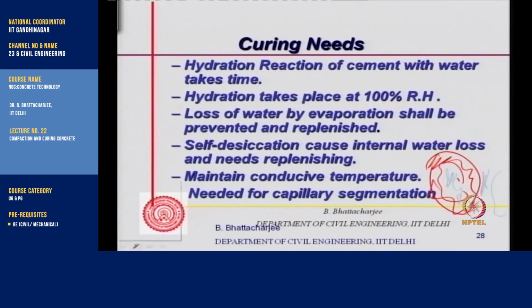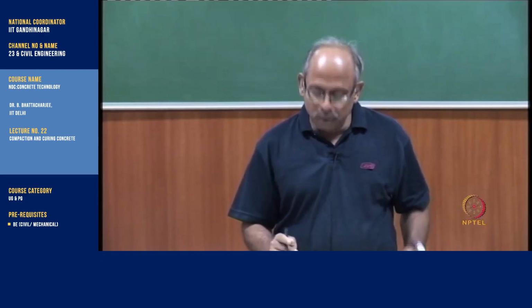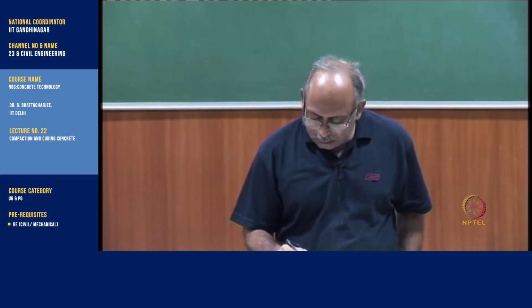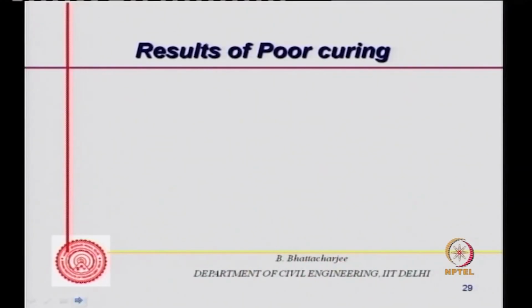Only when you have sufficient hydration product will they come and touch each other from both sides, and the capillary will get segmented. So minimum curing is required in order to ensure that the capillary gets segmented. Otherwise, unsegmented capillary will result in poor durability of concrete.